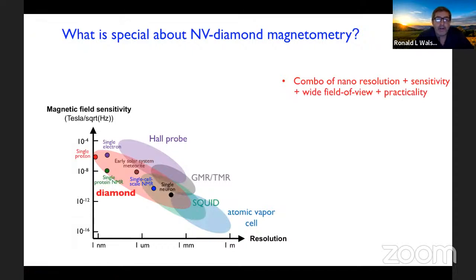This simple chart here shows one of the key parameters, the spatial resolution on the x-axis, and the magnetic field sensitivity in Tesla per root Hertz on the y-axis, with better sensitivity as you go down and higher spatial resolution down to 1 nanometer as you head towards the origin. And I show approximate regimes in which different classes of sensors are useful. Hall sensors for magnetic fields, for example, cryogenic squids, atomic vapor cells, and diamond, typically where it operates from a few millimeters down to sub-nanometer length scales.